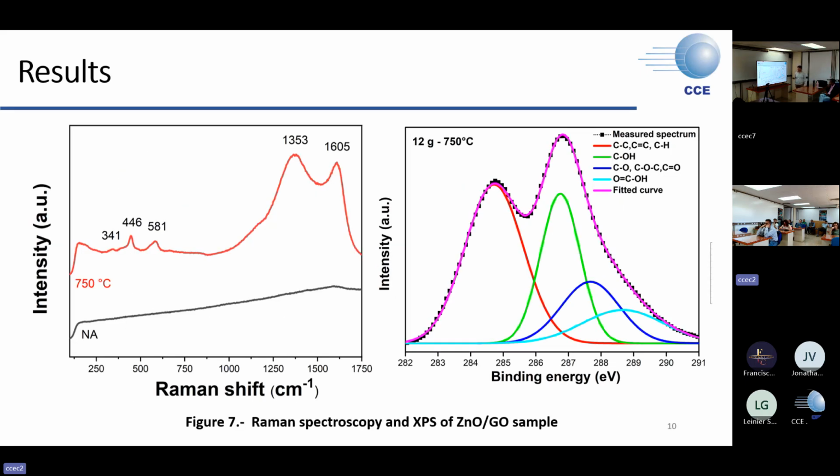We performed Raman spectroscopy, and at this moment we observed that we have some organic material in the compound. We observed the traditional vibrations of zinc oxide associated with the bonding between oxygen and zinc. But we also observed the D and G signals related to the presence of carbonaceous or graphene materials, for example, graphene oxide or reduced graphene oxide. We proved this by FTIR.